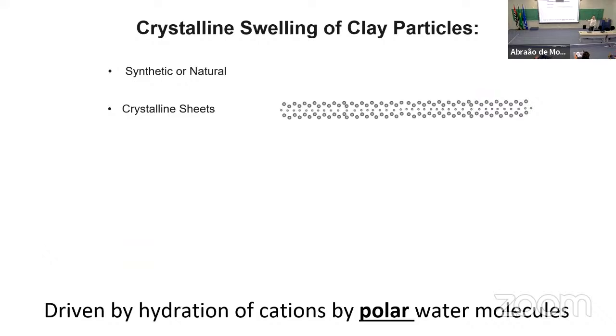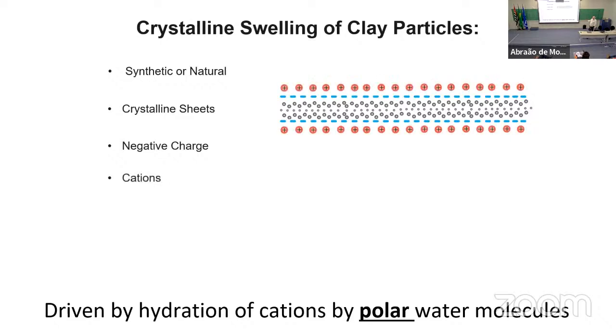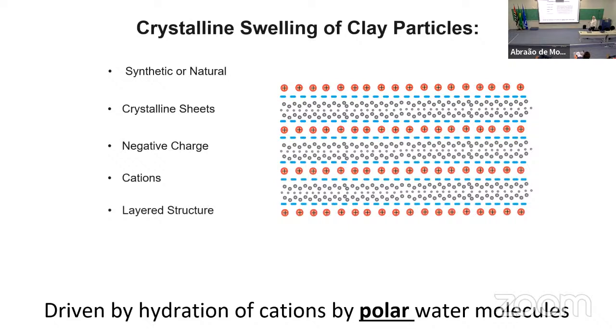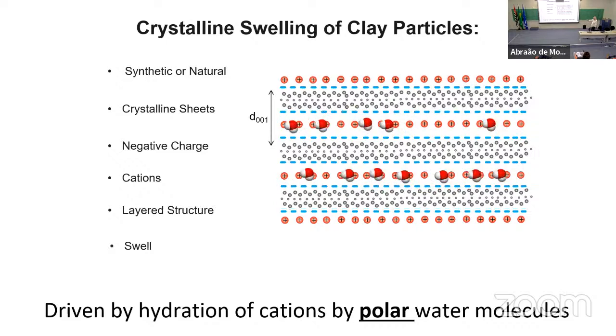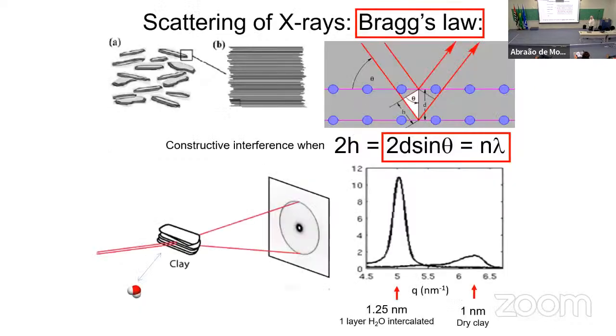What we have are these clay sheets. They are charged, as I mentioned. There are cations there to compensate for that charge, and they stack. When you add water to this system, water can go into the system and the system swells. So you get this change in the d-spacing in one direction, from one card to another. We start off typically at 1 nanometer. The way to measure this is with X-rays, with powder diffraction. It's easily visible in powder diffraction.